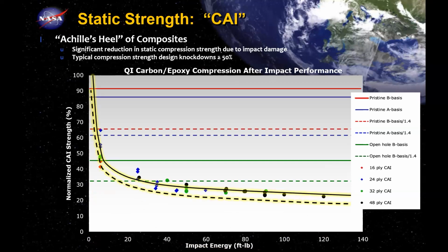So if I'm doing open hole allowables, right? First off, if I was using the pristine strength, even on A basis allowable, I'm way up here, way too high. Because if I do any damage to this component, I'm gonna have trouble. And you can see it drops off, it falls off pretty quickly. Even at 5, 10 foot-pounds, I'm getting huge reductions in strength. And if I look at the open hole compression value that you might get from a material data sheet or testing yourself, that number being around 45% of its pristine.